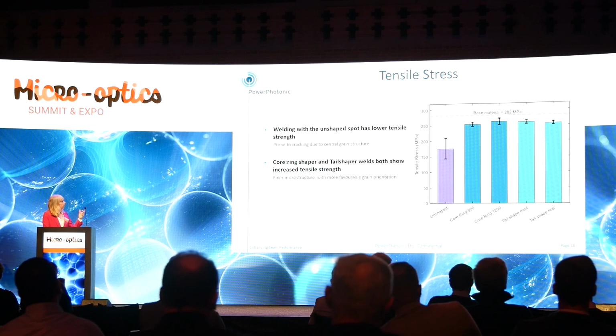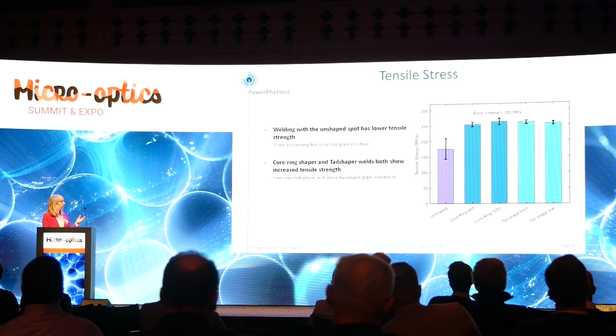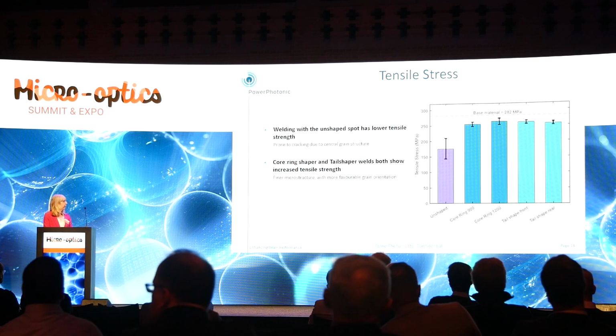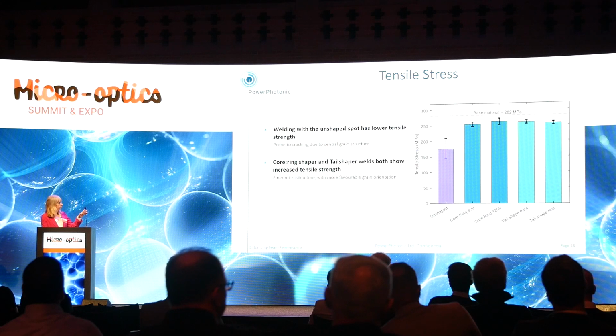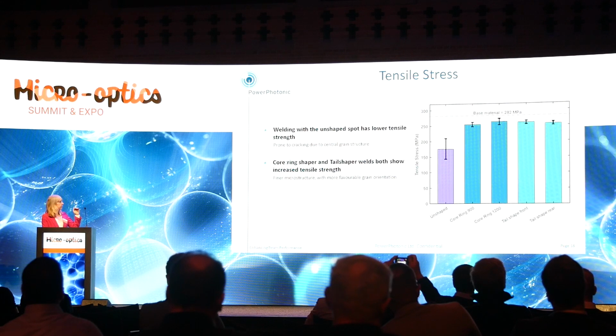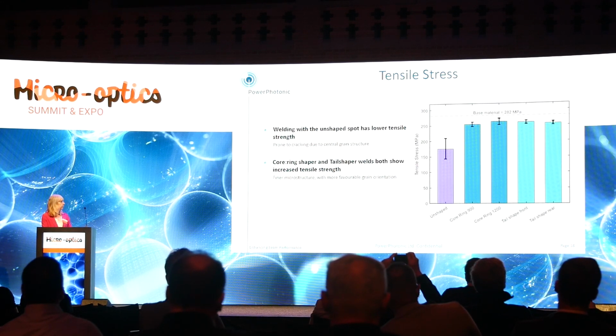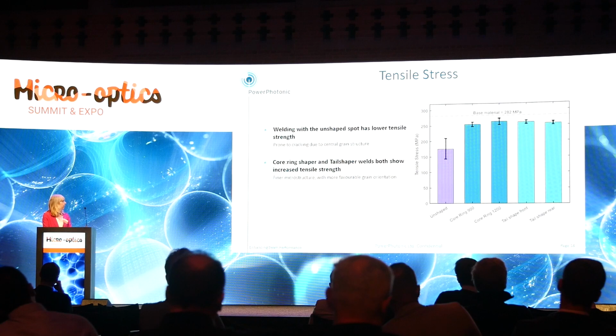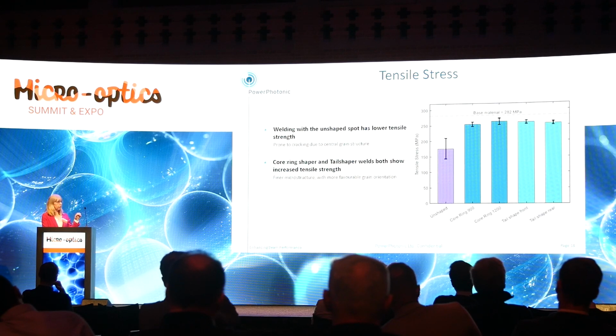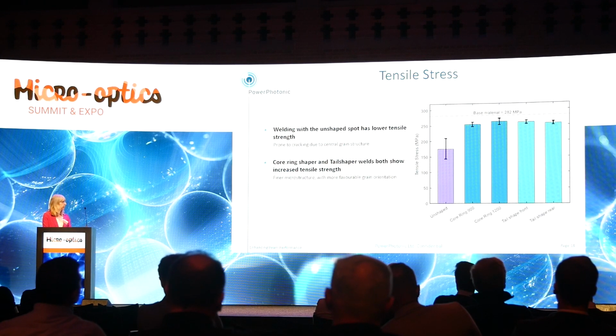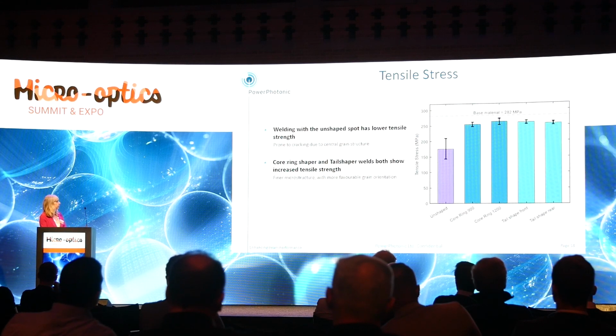So the weld with the unshaped spot was prone to cracking due to the central grain structure. You saw that in the weld, and you can see that the tensile strength was just over half of the base material, but the core and ring, the 1,200 micrometer, and the front tail shaper took the tensile strength back up to almost the base material. So it was a finer microstructure when we looked at it internally, and it had a much more favourable grain orientation, which I think was clear from the video.